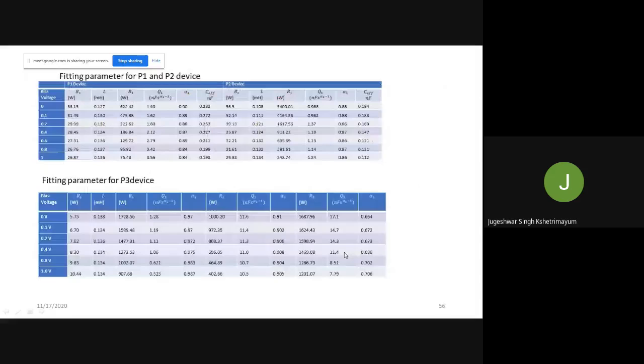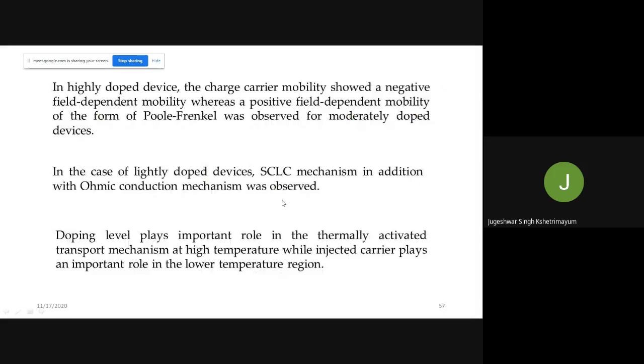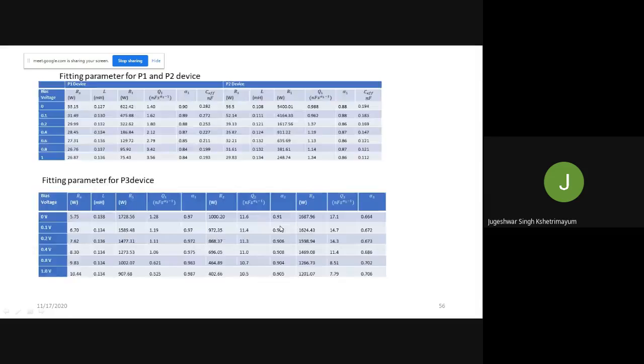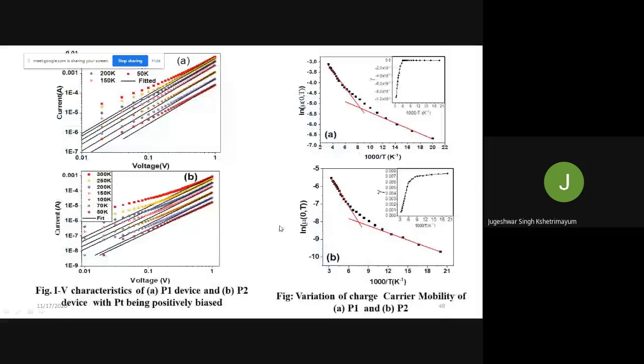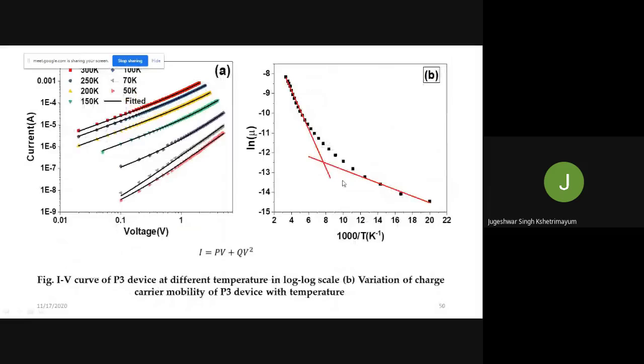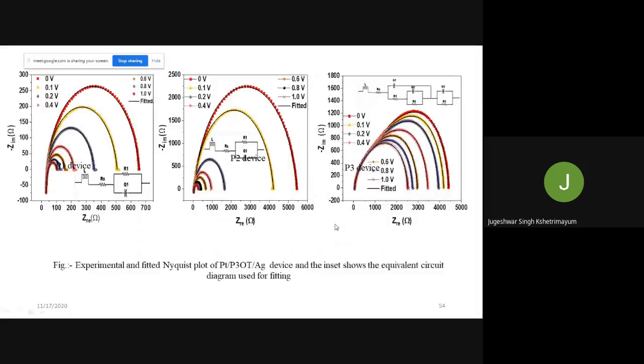Okay, so in the case of lightly doped devices, a space charge mechanism in addition to the ohmic conduction mechanism was observed. Doping level plays an important role in the thermally activated mechanism. The two slopes in the mobility are saying that there are two different types of mechanisms active in different temperature regions.